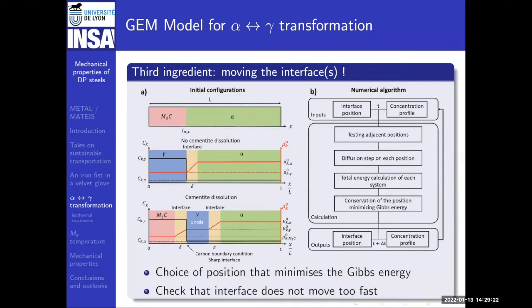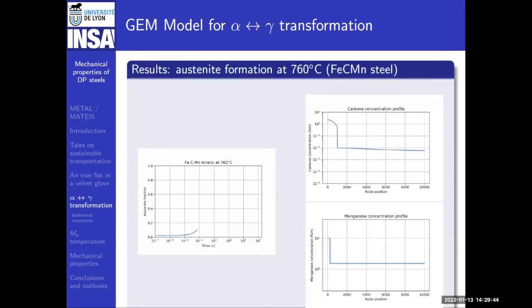And we can have one interface between austenite and ferrite, but we can also have two interfaces between carbide, austenite, and ferrite. I'm not going to enter into detail, but sometimes the presence of these carbides completely changes the kinetics because they can store a lot of solute atoms. Anyway, what does it give?